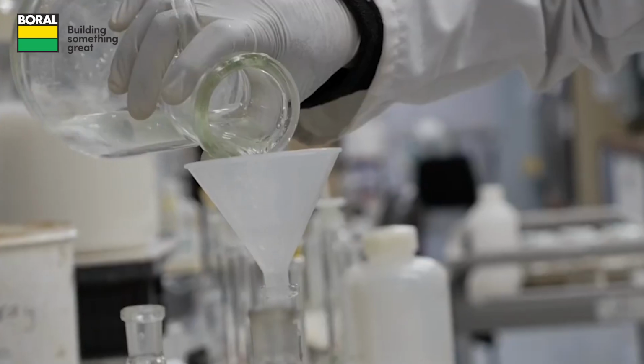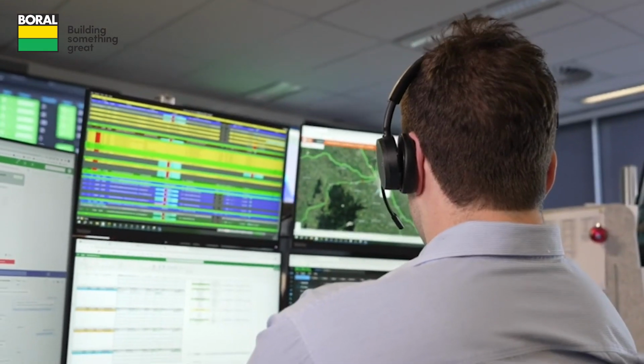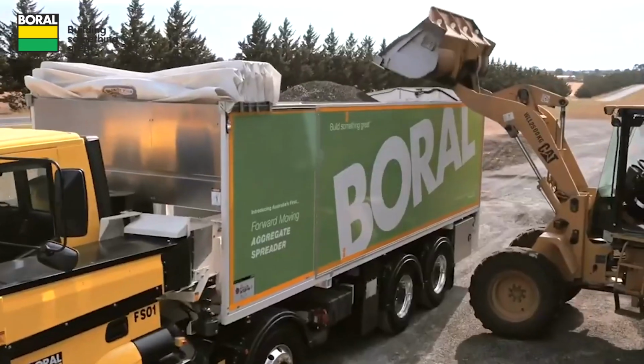Reducing the emissions at source by decarbonizing our cement and concrete manufacturing operations is the key focus for Boral, and we have the ambition to achieve net zero by 2050. We are investing significantly on projects to help reduce our Scope 1 and Scope 2 emissions. For example, we've achieved significant progress in transitioning our key source of fuel from coal to alternative fuel sources. Only in the last 6 years, we've been able to successfully transition from approximately 100% coal usage to providing roughly 30% of the thermal energy used by our kiln from alternative low-carbon fuel sources.